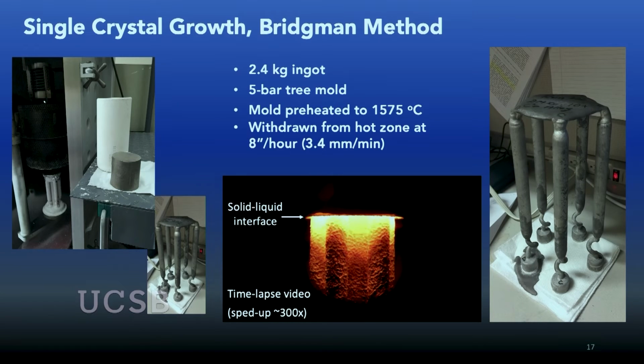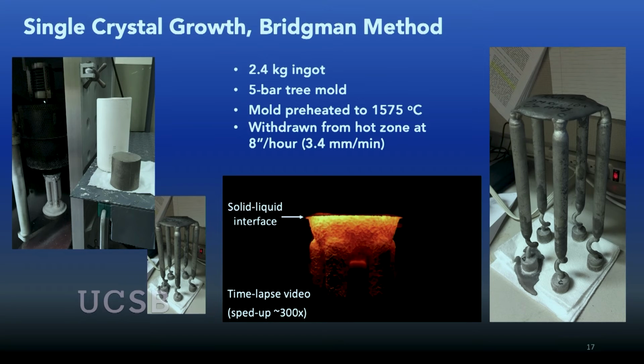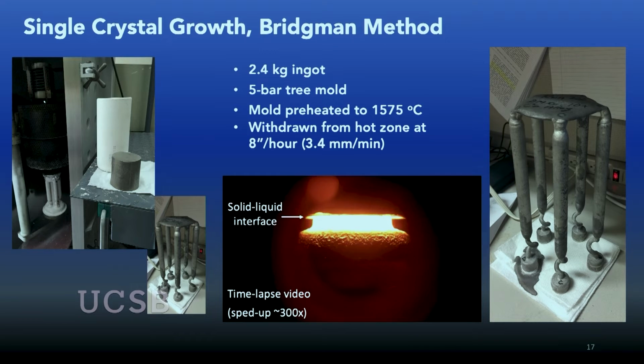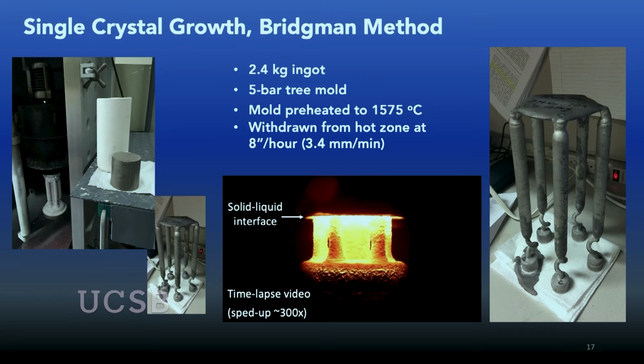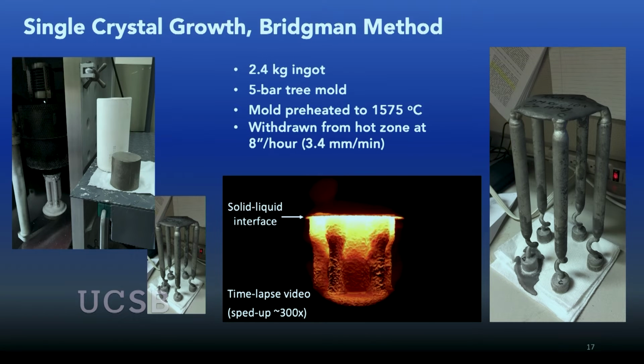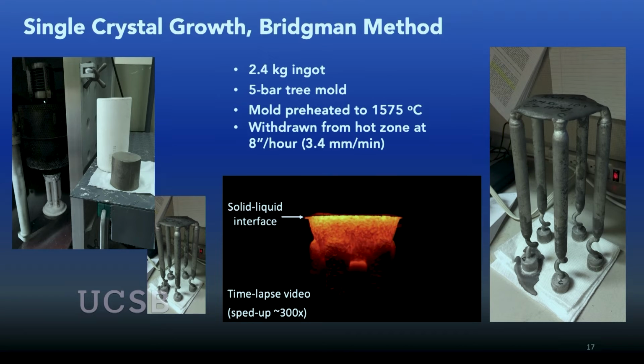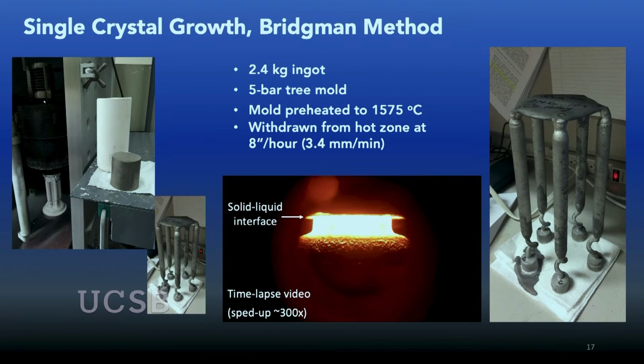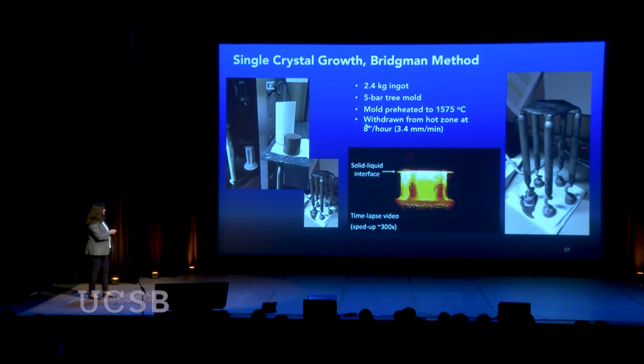So you start with an ingot material. There's a furnace here that you can't see very well that will be preheated to about 1575 C. Inside that furnace will be a ceramic mold, so you melt and pour material into that. And then what one has to do is withdraw from this hot furnace into the cold zone, i.e. you develop a thermal gradient right here. So all the action's right at this interface. And you can see the temperatures changing very rapidly just from the color here. This is a little bit accelerated. You have to do this very slowly at 8 inches per hour.